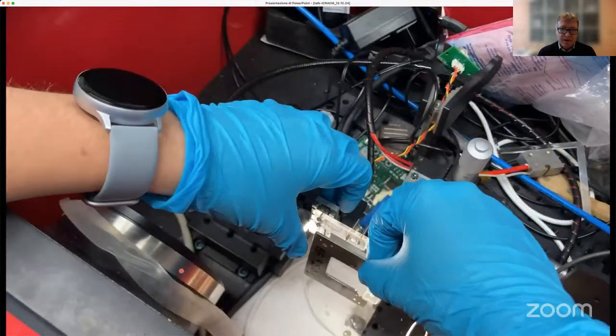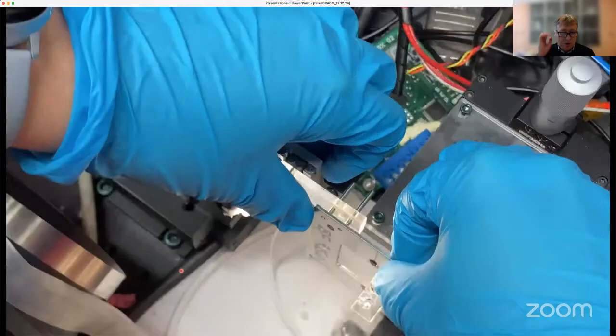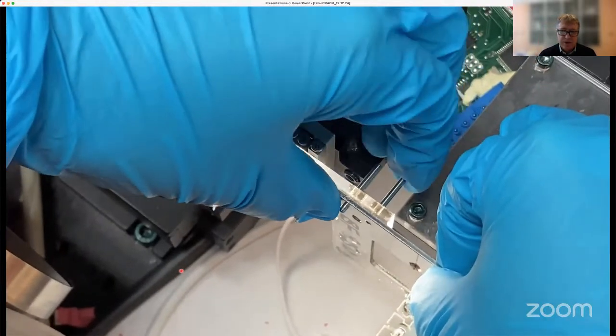How we measured the effect is quite interesting, because we established a collaboration with some colleagues in Finland, in particular the University of Tampere, and also with a spin-off of the University of Tampere, which is Fibrobotics. This company is producing a tool which is very interesting because it allows performing the micro debond test in a much more automated and faster way. Here you can see a movie that we took during the test. It is actually the preparing stage,